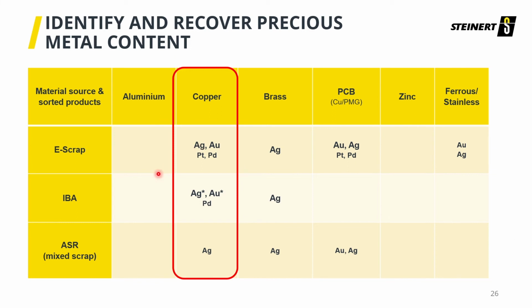When you look at incinerator bottom ash, you're going to see more loose gold and loose silver. That's what the asterisks are there to denote. So this may be things like jewelry or the classic silver spoon that we pull out of the stream. This is going to be more loose, kind of approximate maybe 50% of the gold and silver content out of IBA is that loose fraction. And then specifically for ASR, when you look at that, you see a lot of silver. And this is silver that's used in coatings, platings, mostly on the electrical connectors that are used in the autos industry.